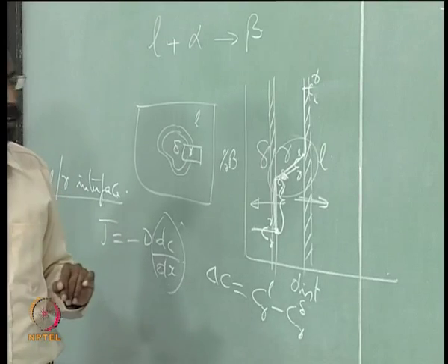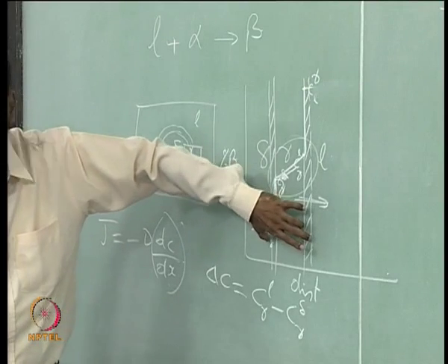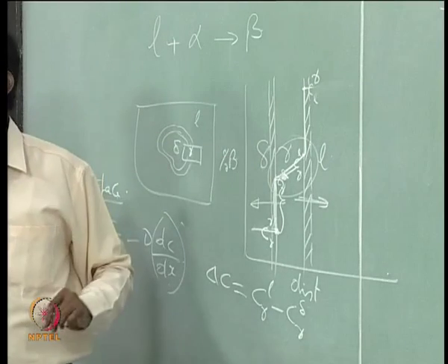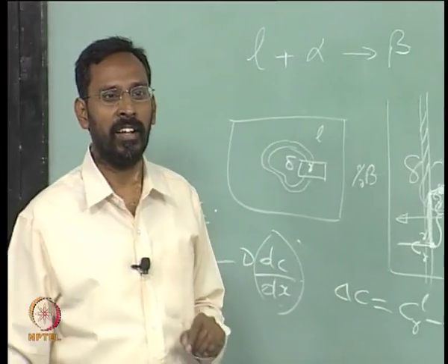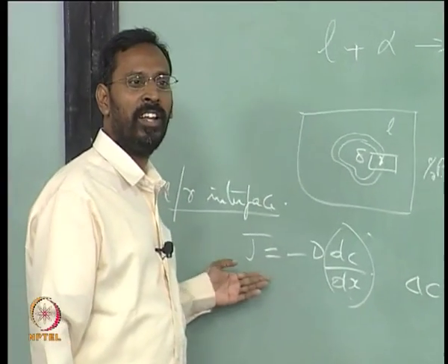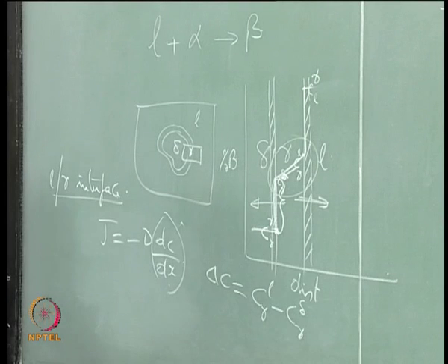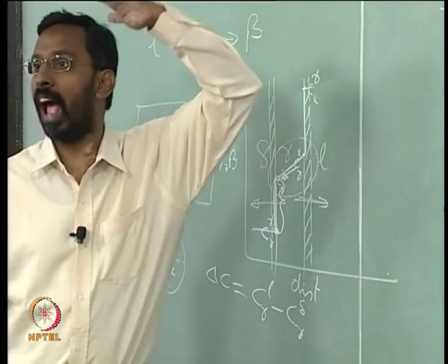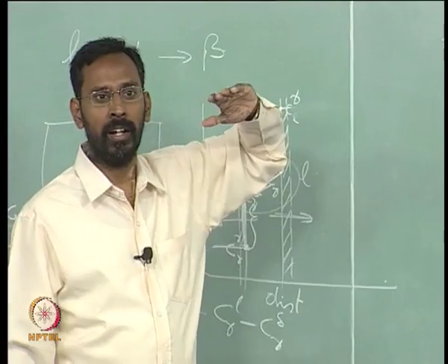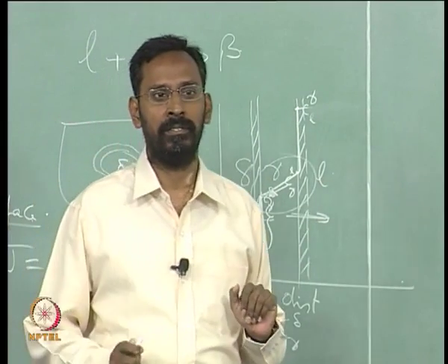So, what is now the gamma thickness? Gamma thickness is thicker than what it was before. So, if the gamma thickness is increasing, in our equation the denominator is increasing, dx is increasing. If the dx is increasing, obviously the gradient decreases, and if the transformation is taking place at a fixed temperature, dC is always constant.